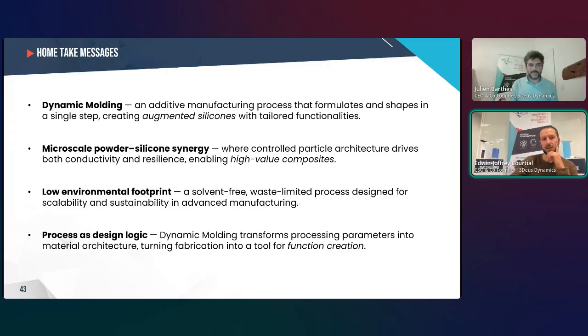Second, the microscale synergy between the powder and silicone gives rise to unique material architecture. This controlled microstructure allows us to integrate conductivity, thermal resistance, or mechanical compliance without compromising elasticity. Third, dynamic molding stands out for its low environmental footprint. It operates at room temperature without solvent, with recycled raw materials and minimal energy consumption, combining performance and sustainability.